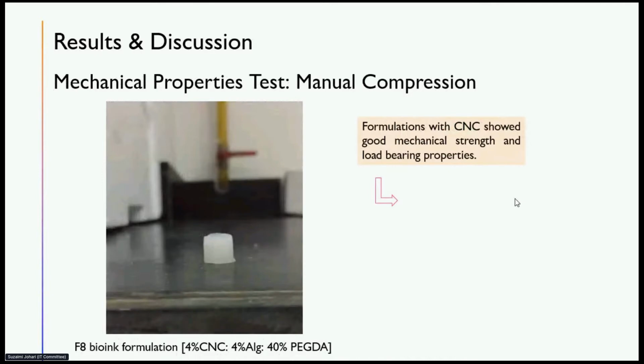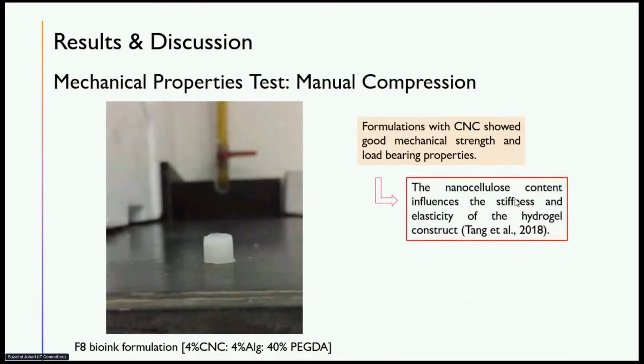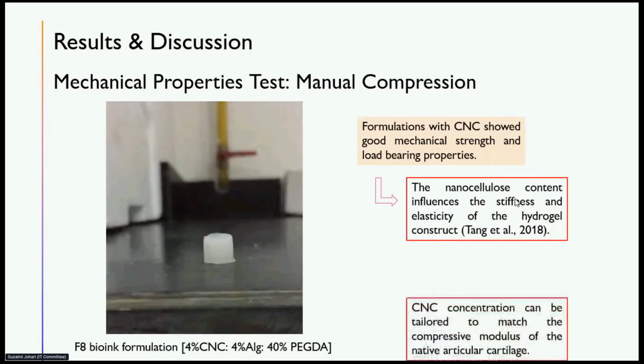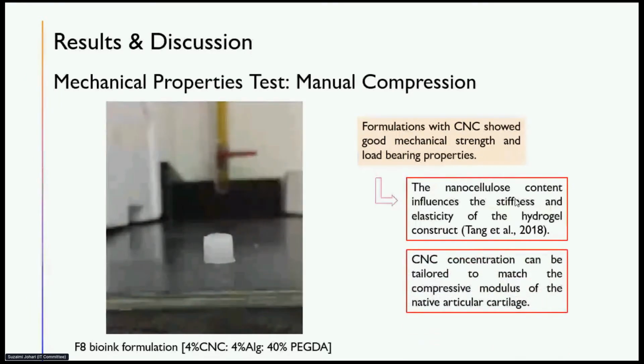Okay, so from the study done by Tang and colleagues, they actually reported that the nanocellulose content influences the stiffness and elasticity of the hydrogel construct, which means that we can actually play around with the CNC concentration to make it match the compressive modulus of the native articular cartilage. So this will be good for future studies if we want to do further study. Next slide.